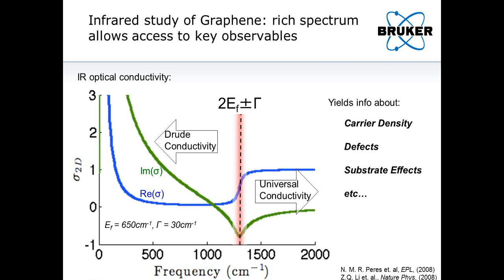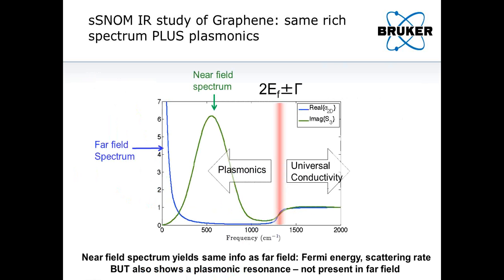Now, on the next slide, I would like to show how near-field infrared spectroscopy can also be used to characterize graphene in much the same way. So I also calculated a spectrum that you would get using near-field spectroscopy. Now, the difference is that this spectrum would be using infrared light of a much larger spatial frequency, because now our point source is really close to the graphene. We have access to these huge spatial frequencies, these huge momenta. Because of that, we're able to excite plasmons. And that's what gives rise to this additional feature that's not seen in the far-field spectrum.